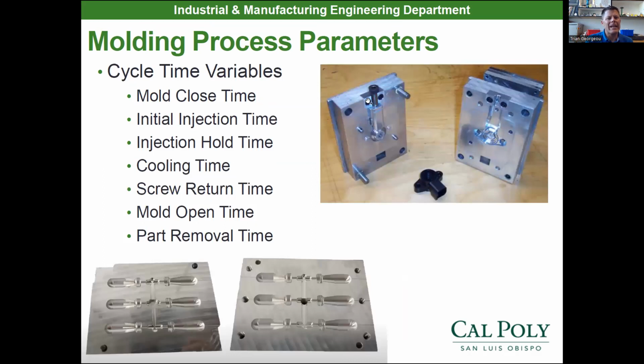Now, when we're doing a cycle time on our mold, you're going to see that's an old set of Geneva handle molds down there in the bottom left. That's when we did 6 at a time. We redesigned the molds to do 2 at a time, and we made it so it flashes a lot less. Those thinner molds that you see down there were flexing, and they were causing a lot of flash. So we made our molds out of 1-inch thick aluminum. That was 3/4 inch thick aluminum down there. Nevertheless, the cycle time is going to be included in your injection molding lab.